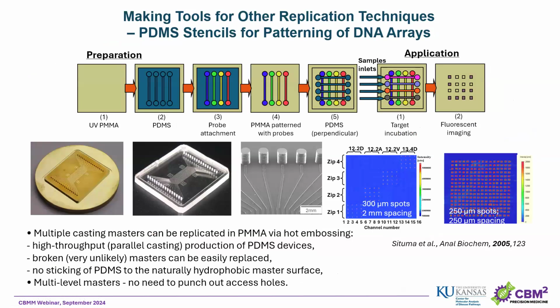I gave you the reason why we're interested mostly in this technique, because we're using thermoplastic, but you can actually use micromilling to make tools that let you fabricate devices by other techniques, like for example, by casting PDMS. So we can use milling to make tools for PDMS casting. We showed the application for patterning of DNA arrays, where we would take the PDMS device, lay it on the UV modified PMMA, first run different oligonucleotide probes through those channels, and then by putting our cast device perpendicular, we could read different samples in the microarray format.